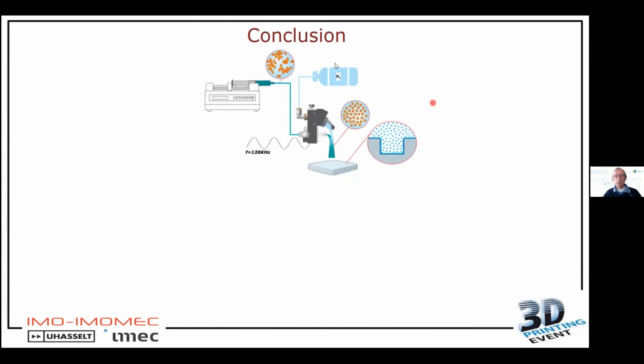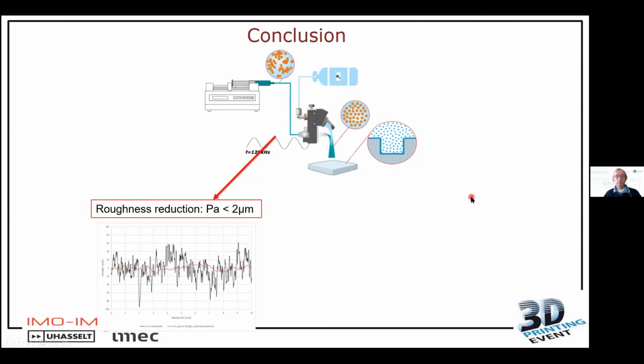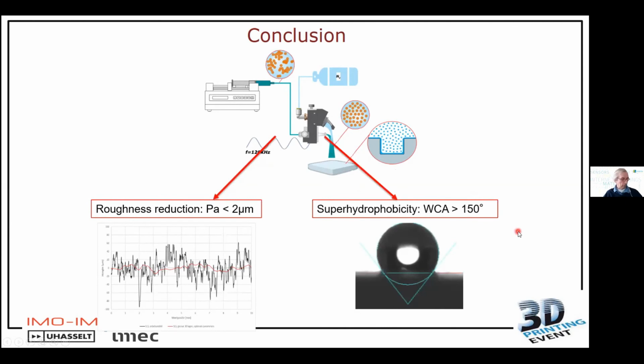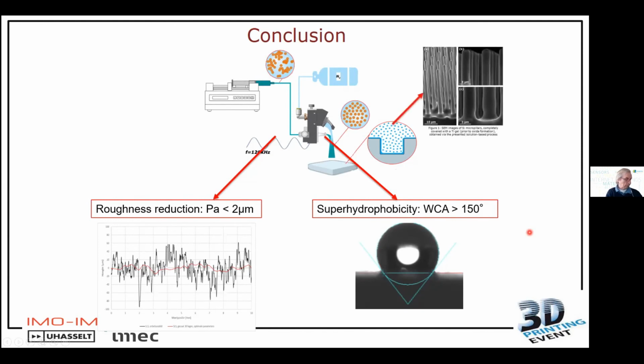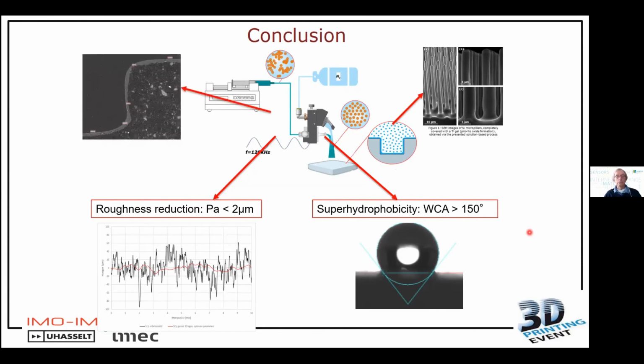So to conclude, I can say that we used ultrasonic spray coating, which is very interesting because you have a droplet generated, which is very homogeneous and of which you can tune the speed at which it touches the substrate. We showed roughness reduction below 2 micrometers for SLS printed parts. We showed that by adding nanoparticles, we could go to a contact angle bigger than 150 degrees, going to superhydrophobicity or easy to clean properties. But we also showed that you can also use it for high aspect ratio coatings, conformal coating, and also for other 3D objects to be coated.